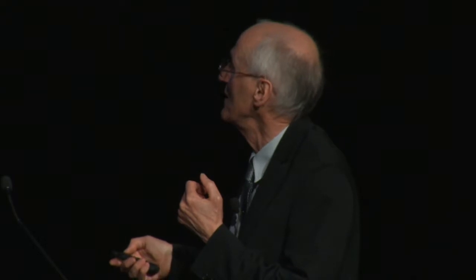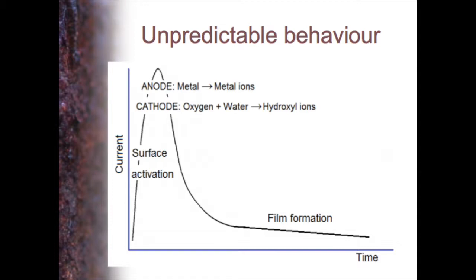Why is it that we can't just use those potentials? The main issue is that if you do this sort of test by itself, all that's happening is the metal is corroding and going into solution and staying there. But in the real world, the metal would be activated — as soon as you join the two metals, the current would start rising, but then we'd start getting protective films with time. If you leave it, a film will build up affecting the corrosion.